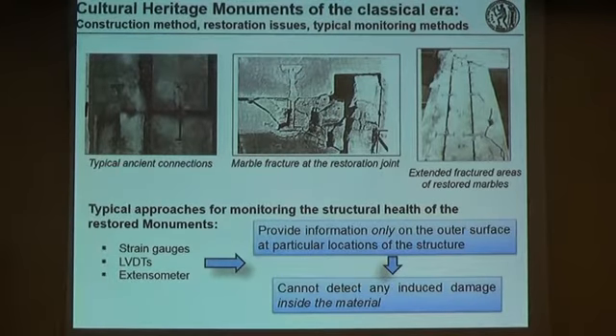Typical approaches in order to monitor the structural health of these restored monuments involve the use of strain gauges, LVDTs, and extensometers. All of them provide information on specific locations of the outer surface of the structure. Failure mechanisms, however, that led to the fracture of these restored marbles initiate from inside the structure. However, traditional monitoring techniques cannot detect any damage that occurs inside the material.